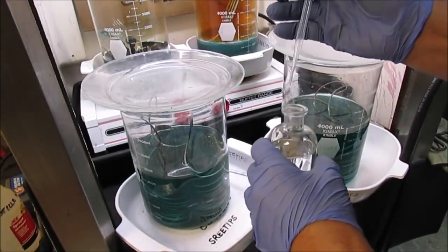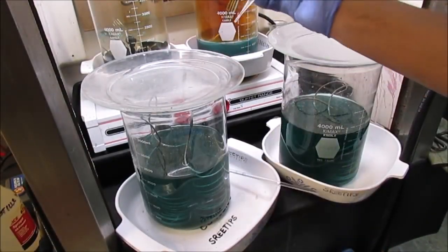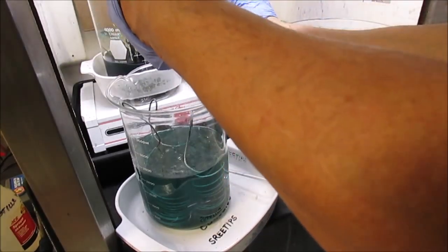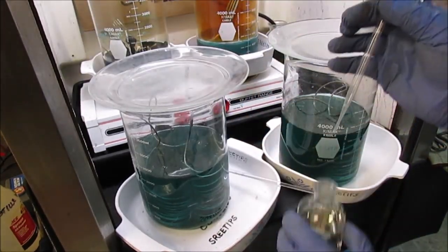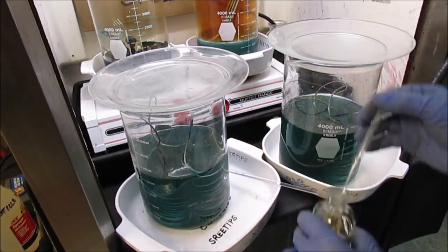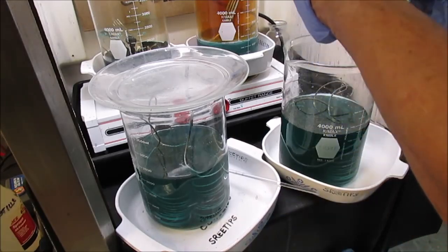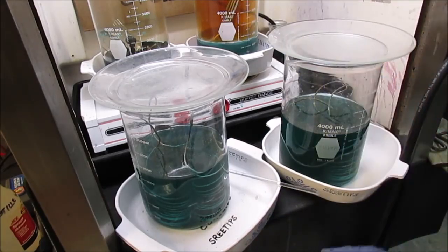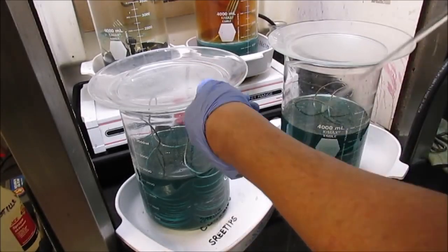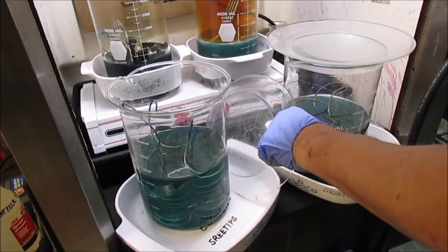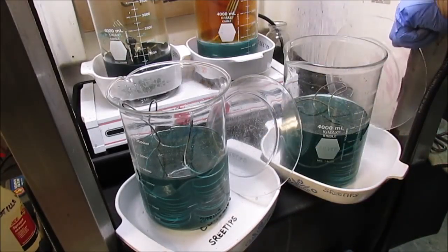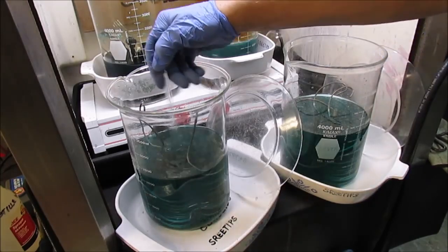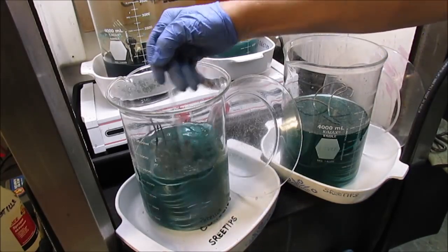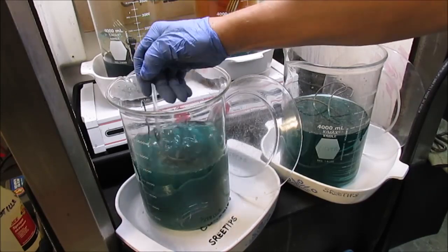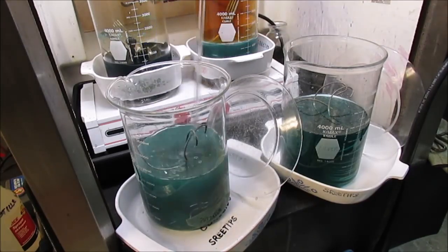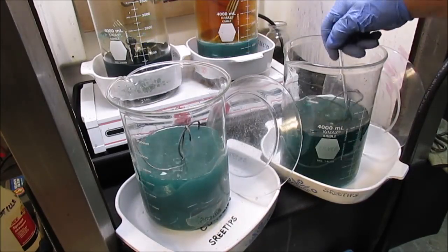Here's some nitric acid. I'm going to pour about 1 ml in each beaker here. That should be enough to get this started. Now I'm going to stir it up. Here I'm starting to get a little frustrated, but this will end up being a valuable lesson in silver refining on how not to add too much of that concentrate when cementing the silver on copper.